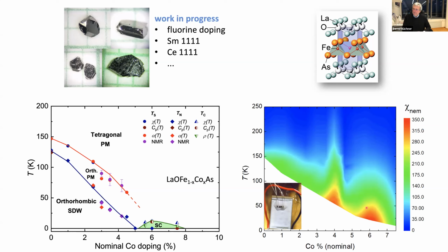Of course, the lattice picks it up. And then this thing of disorder, which you mentioned, I think that's very important, in particular to understand this funny phase diagram where we somehow lose our structural phase transition. Here it's fairly sharp, a very nice phase transition, and then you start to dope and it becomes broader and broader. In the same samples, the other transition becomes sharper and sharper. So it's not some sample property, it's something more intrinsic.